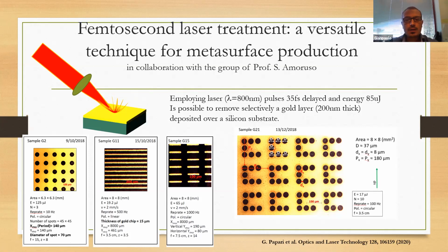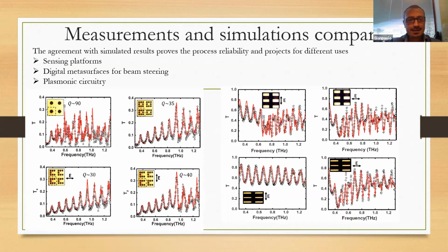For the samples, of course, we start with a substrate of silicon with 200 nanometers of gold on top, and then we ablate partially. And this is basically the main achievement, where we have overlapped to our experimental results, in this case just the transmission modulus, the simulation results.